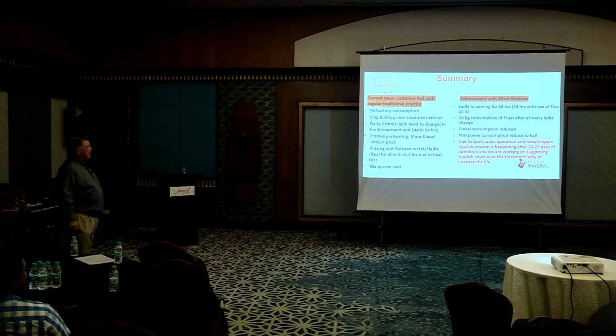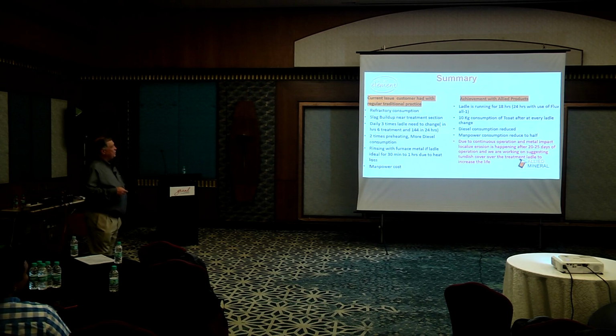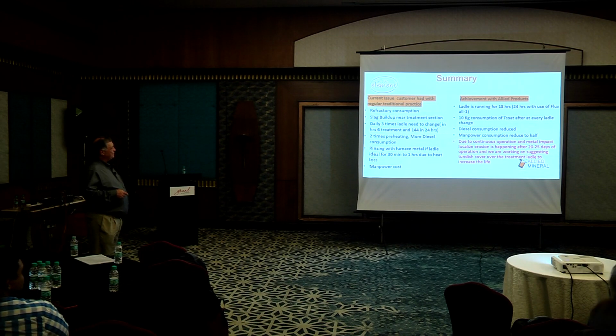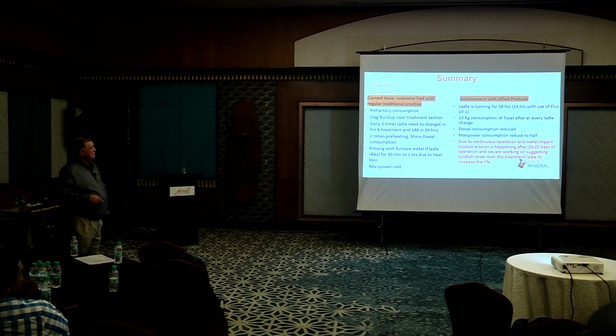Manpower cost was higher. So ladle running for 18 hours, okay? With the use of flux also. 10 kg consumption of T-coat, okay, much lower. Diesel consumption reduced, manpower reduced. Due to continuous operation, the metal impact localized area is happening after 20-25 days, so we're working on suggesting a tundish cover over the treatment ladle to increase the lining life.